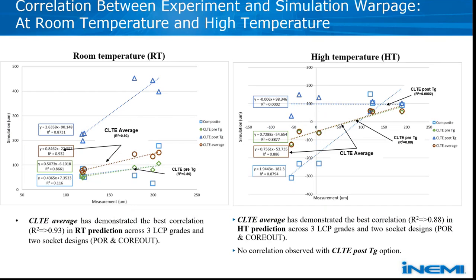So here the thermal correlation analysis was conducted to assess the accuracy of the proposed molding model for various LCP materials in both POR and core design under room temperature and high temperature conditions. A room temperature warpage correlation comparison for various modeling methods is shown in the left plot. The composite model recorded the weakest correlation with measured data.